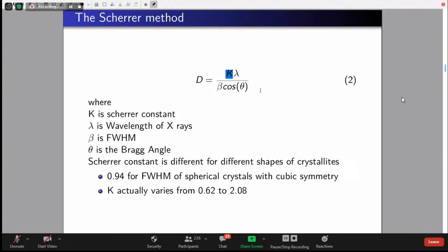What they say is, if it is a spherical crystal, the rest of the things are small aberrations, where we can give 0.94 as a safe value for the Scherrer constant. But afterwards, people have done a lot of research on this. However, the Scherrer formula is going to give us either overestimated or underestimated values, because Scherrer is not going to bother about how much strain is in the sample, because the entire broadening is given only in one single parameter here, beta.